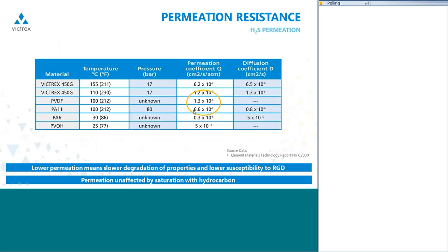Also, of course, lower permeation means slower degradation of the properties in your composite, because aggressive chemicals are permeating much more slowly. But also, it means a lower susceptibility to rapid gas decompression. The fluids and gases find it much more difficult to travel through a PEEK barrier. Permeation is also, quite uniquely I think, in PEEK unaffected by saturation with hydrocarbons. So if your pipe precursor is fully saturated after many years of service with a hydrocarbon, it won't affect the rate of permeation through. There won't be a sudden onset of additional permeation.